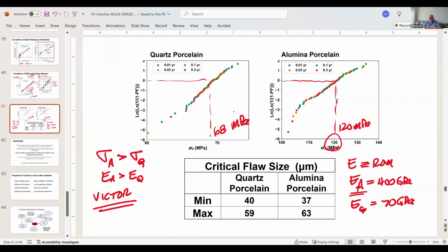So, obviously, that makes sense. So I get a stronger sample. So then, though, when you look at the calculated critical flaw sizes, the maximum critical flaw size for a quartz porcelain is 59 microns. The maximum for alumina is 63 microns. The minimum is 40 versus 37. These two samples have exactly the same flaw population.